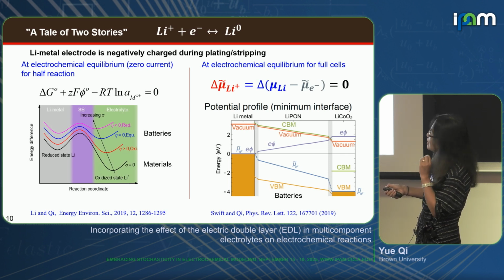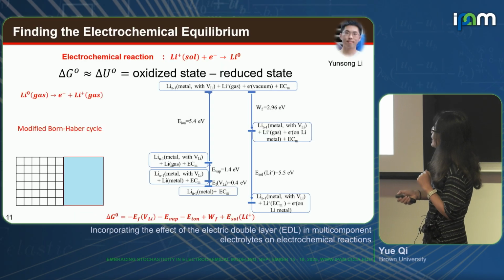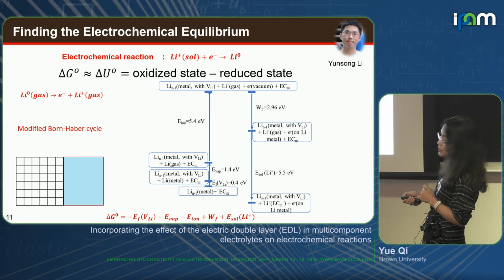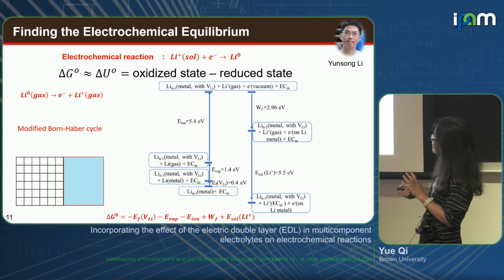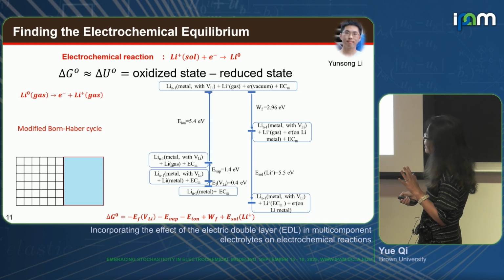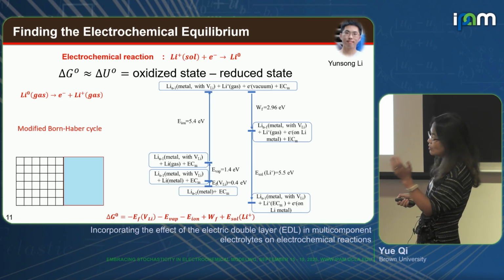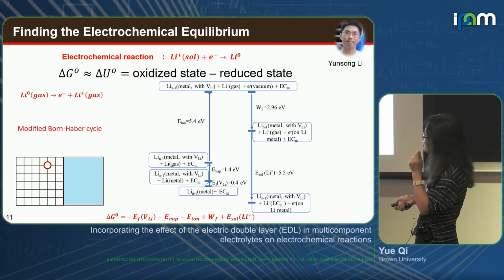electrolyte after the reduction. But in this case, if we have this reaction, the lithium has to become part of the metal, right? So the cohesion energy is important. So we modified the Born-Haber cycle a bit. So we say we want to really know this energy difference of this reaction. You can argue my calculation numbers can be more accurate, but the first level of approximation is the cohesive energy is now replaced by a vacancy energy. If I take a lithium out, I have to create a vacancy, and that's the vacancy formation energy.